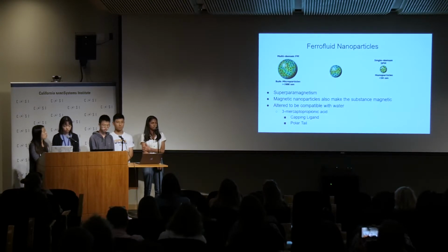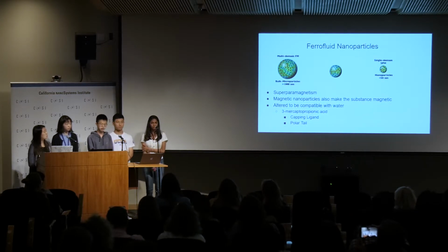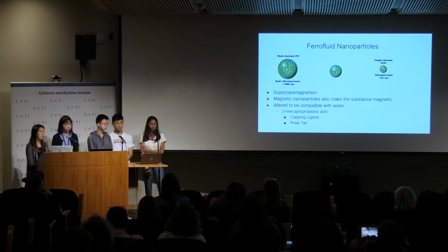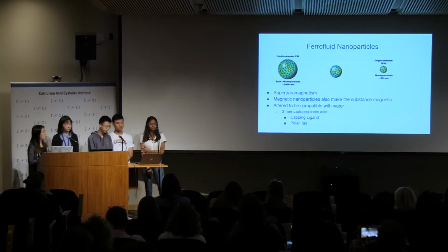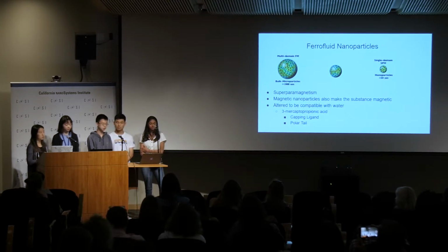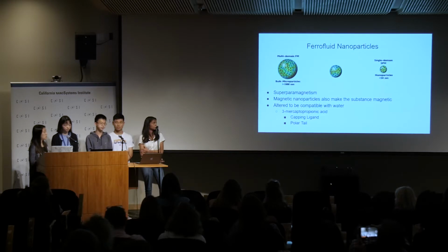Magnetic nanoparticles also make the substance they're in magnetic, and we had to alter our nanoparticles to be compatible with water. We use 3-mercaptopropanoic acid, and this is a capping ligand we use to cover the nanoparticle, and this is a polar tail, which is able to be suspended in water.